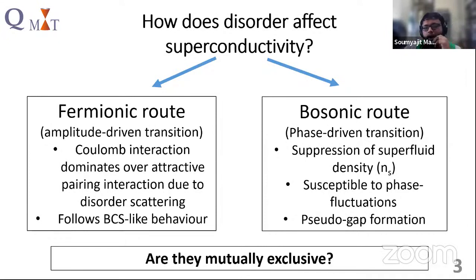On the other hand, for the bosonic case, the superfluid density itself gets suppressed due to disorder, and the superconductor becomes more susceptible to phase fluctuations. So eventually, at a critical disorder, the superconductivity gets destroyed because of the loss of phase coherence, and then we can see a superconducting gap even above the transition temperature. We call it a pseudogap, and we can detect the pseudogap in our scanning tunneling spectroscopy measurements.